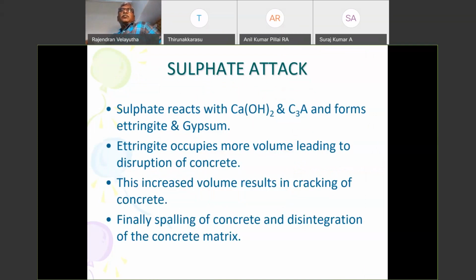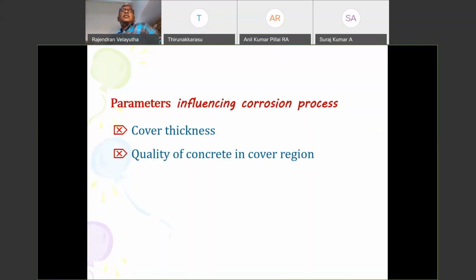The other one is sulfate. Sulfate, we all know, reacts with the calcium hydroxide and C3A and forms ettringite, which occupies more volume. As it occupies more volume, it pushes the cover concrete, and finally spalling takes place, the rebar is exposed to the environment, and it results in corrosion. So the parameters for this are very, very important.